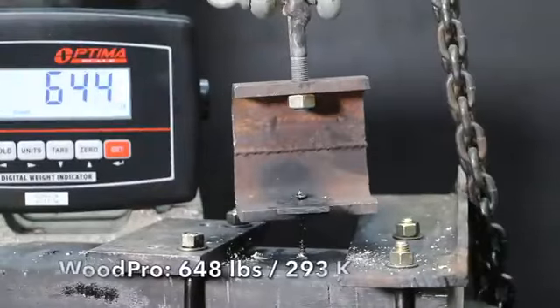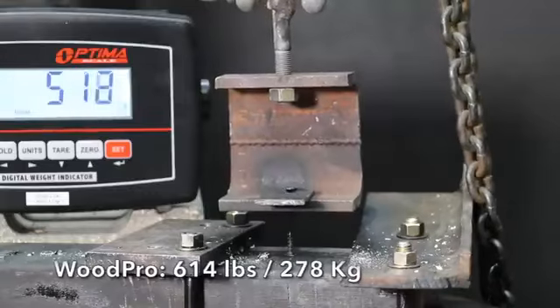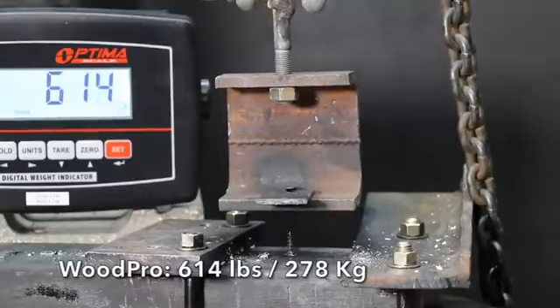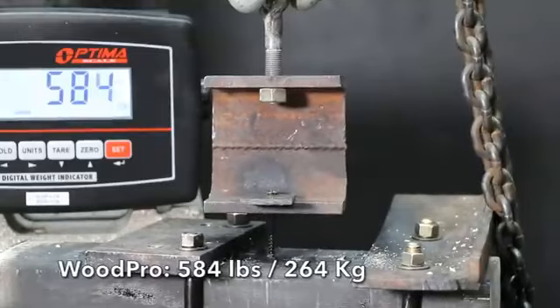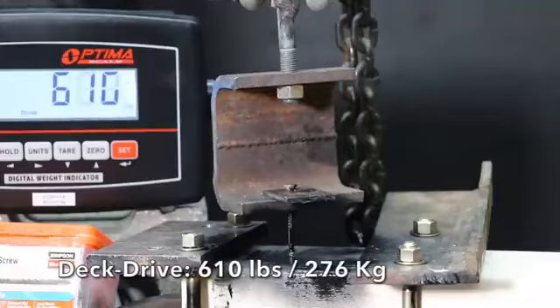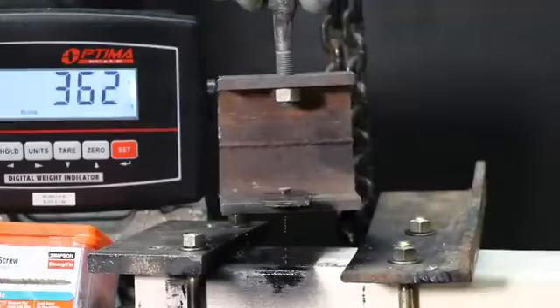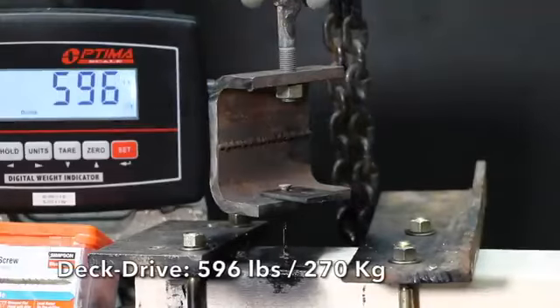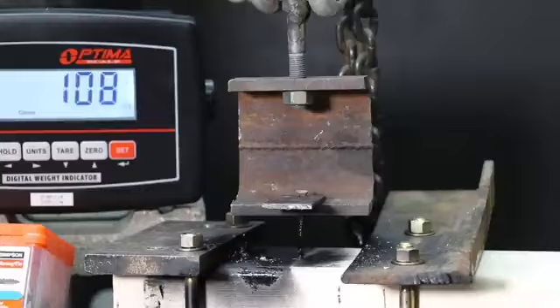Even though the WoodPro is a number 9 screw, it still performed very well on the first screw at 648 pounds. The second WoodPro screw gave up a little sooner than the first at 614 pounds. 584 pounds on the third screw for an average of 615 pounds. The Deck Drive performed fairly well on the first screw at 610 pounds. The second screw was nearly the same as the first at 596 pounds. 548 pounds on the third screw for an average of 585 pounds to move into third place behind the WoodPro.